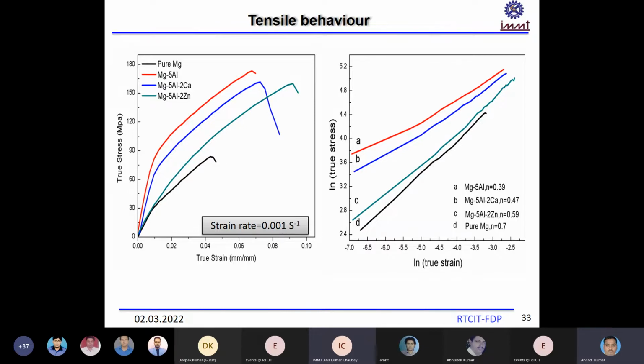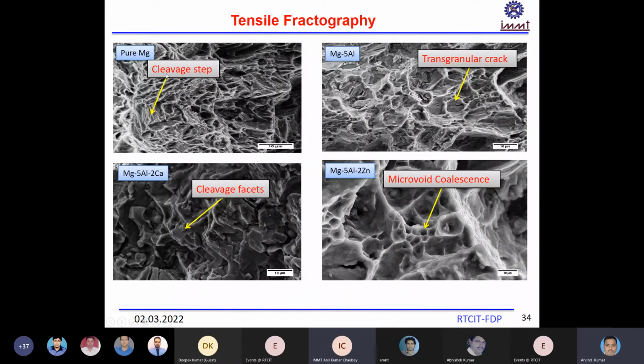In the case you want to use the zinc, but actually the aim is not completed in this study, so that's why here you can see the fracture surface. Also here, the pure magnesium, you are seeing that this is kind of brittle, a mix of ductile and brittle type of fracture. But the aluminum, when you are adding more and more, it goes to brittle. You can see that this is the intermetallic phase, which is a region that becomes completely brittle. And that's why it fails at a very low ductility.